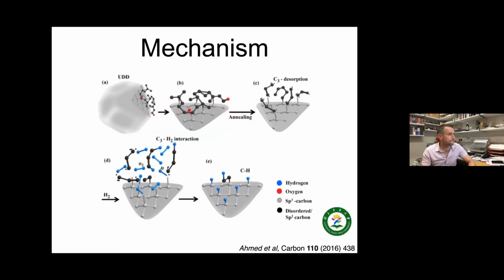And so they came up with a basic model. Obviously we can't prove this because you can't really look at this. What you could probably do is something like cavity ring down spectroscopy to see if you can see C3 absorption. But I suspect the signal is so weak, you would need someone like Mike Ashfold to be able to do that. It's pretty special. So the idea is that you have your UDD, there's a finite concentration of sp2. You heat it up, it forms C3. The C3 could easily crack the H2, which can then terminate the surface. Like I say, I can't prove that, but it's possible. So that was super interesting.